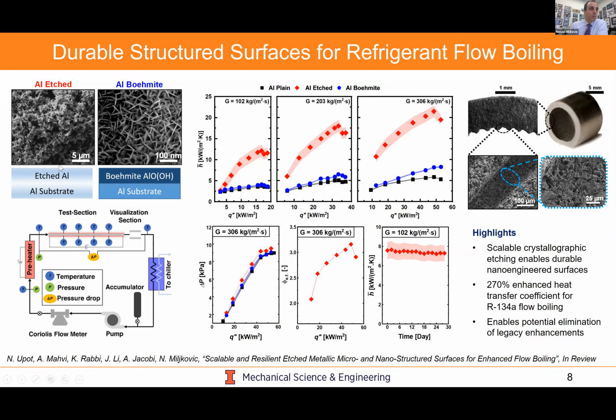What crystallographic etching allows you to do is to have a nice uniform metallic composition of the structures that matches your substrate, which is shown by the schematic down here. It also allows you to tune the structural length scale to get it to the point where nucleation flow boiling is enhanced, and you could see an enhancement. So by doing rigorous heat transfer quantification, here we plot the flow boiling heat transfer coefficient as a function of heat flux for 3 different mass fluxes. We see that if we use the conventional nanoscale boehmite surface, there's no difference from the bare. But if we use our aluminum etch surface, we're able to demonstrate on the order of 3x enhancement.